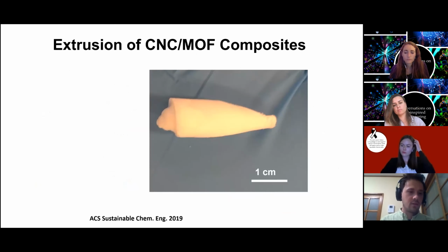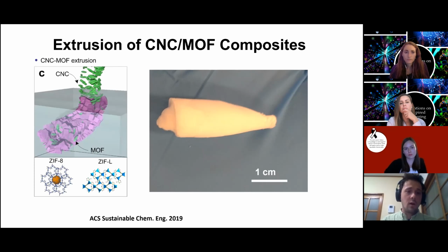The cellulose nanocrystals are a bit interesting, and we can make these very beautiful large aerogels from cellulose nanocrystals in moulds. The way we do that is essentially we extrude cellulose nanocrystals with a pipette or a syringe or whatever you want into the precursors for the moulds.